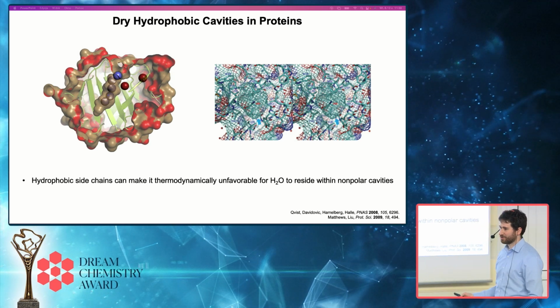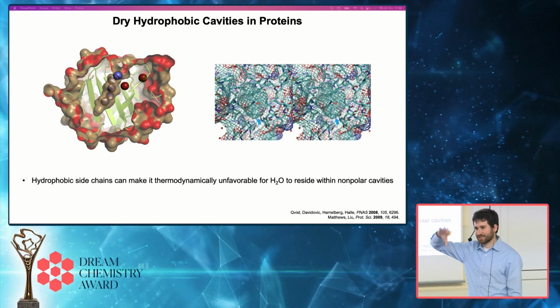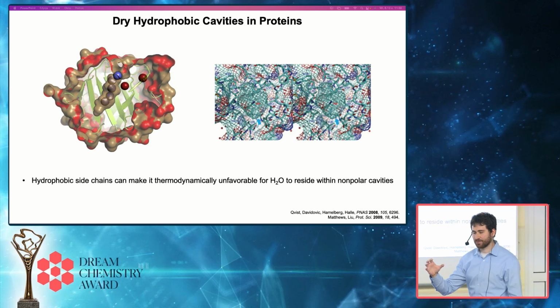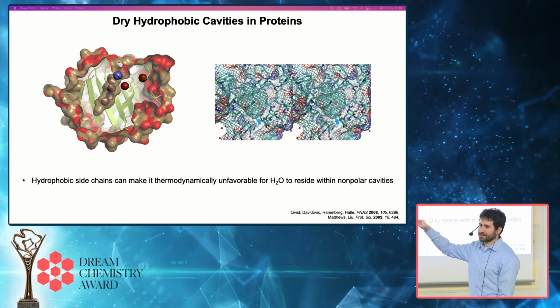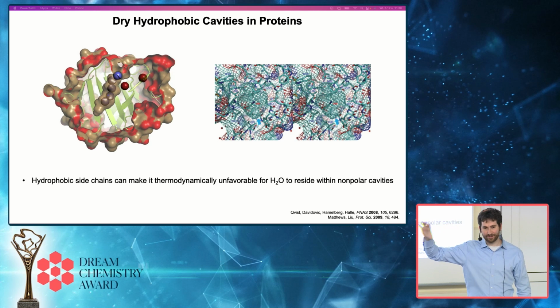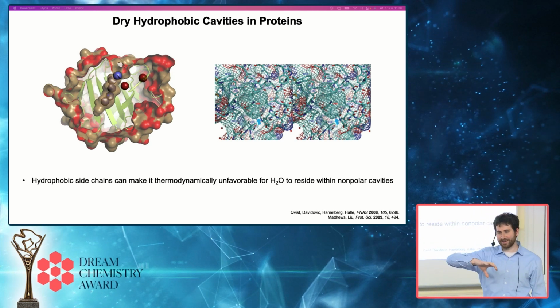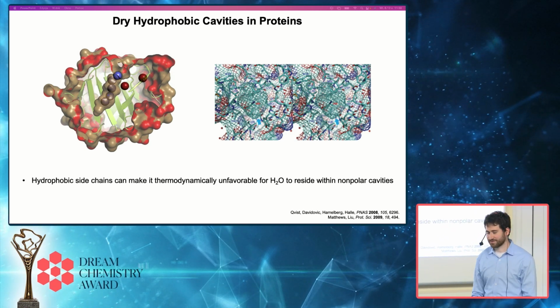So entropically unfavorable because water molecules have fewer degrees of freedom when they're confined inside these hydrophobic pockets than in the bulk phase, and enthalpically unfavorable because water-water interactions are stronger than water interactions with these hydrophobic surfaces of these cavities.